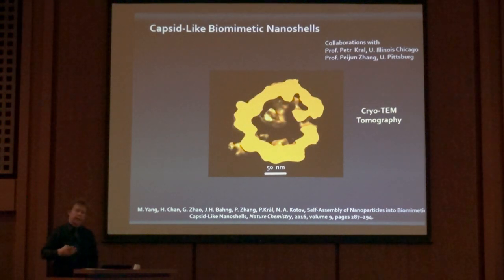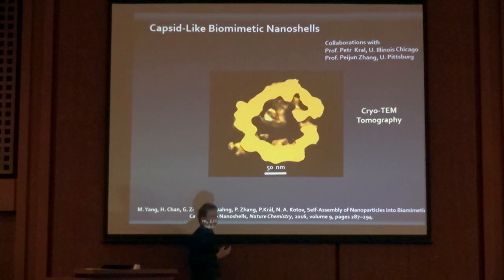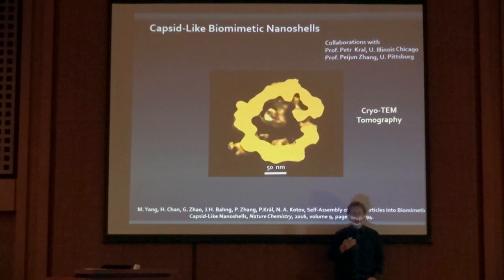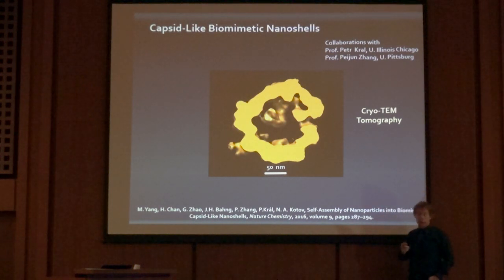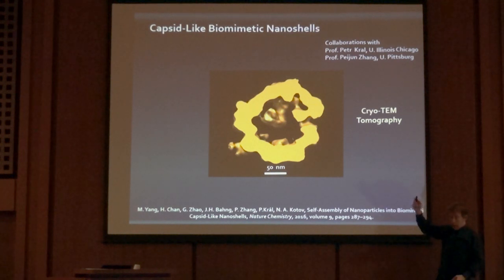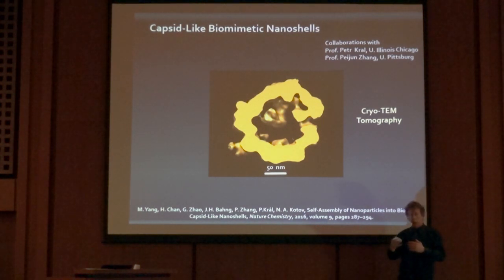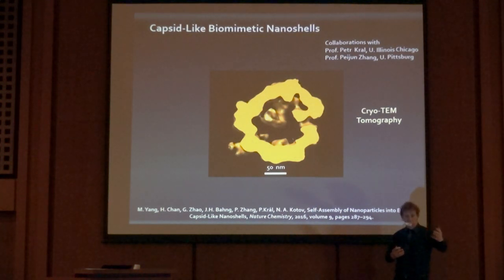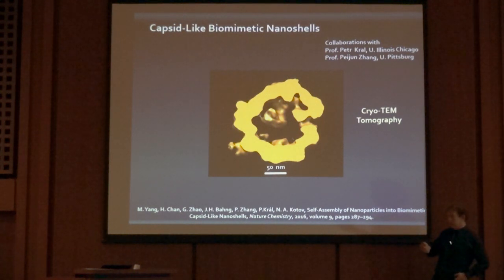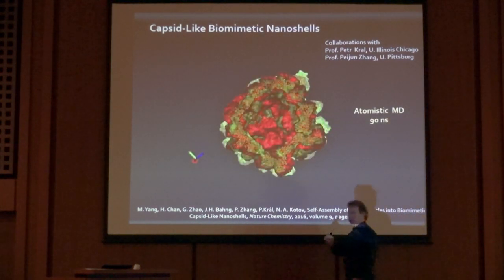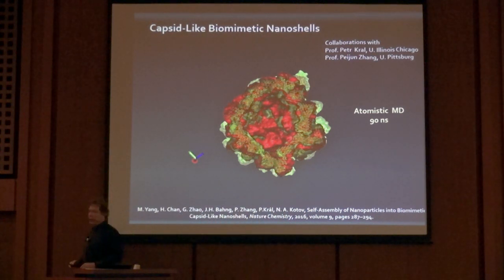One of the reasons why this system is also attractive is because it offers an interesting opportunity now to transition from empirical description of these assemblies into very concrete and exact description by using computational science and, for instance, molecular dynamics, which in this case was helped by Dr. Kral. In many other cases, it was also demonstrated extensively by my very good colleague. The power of these methods can be represented by the fact that this experimental transmission electron microscopy can be replicated almost exactly on the computer by the molecular dynamics.